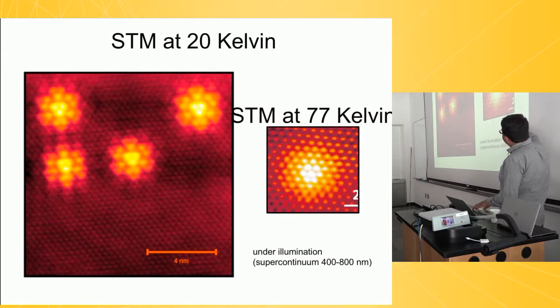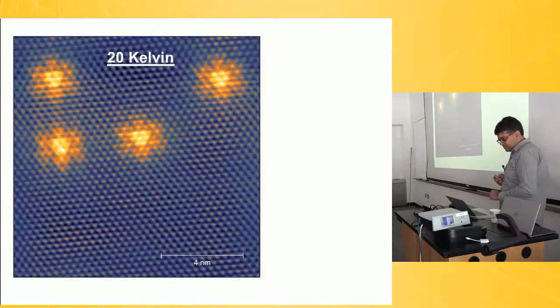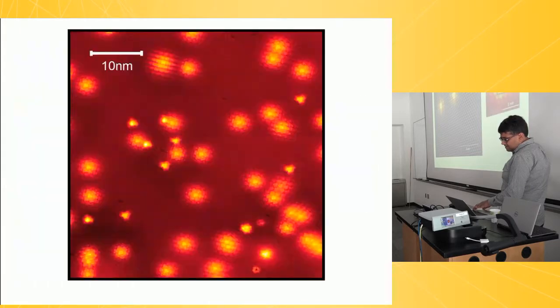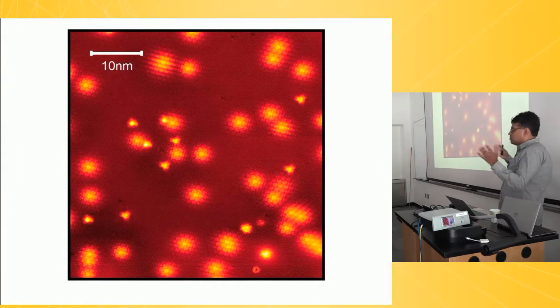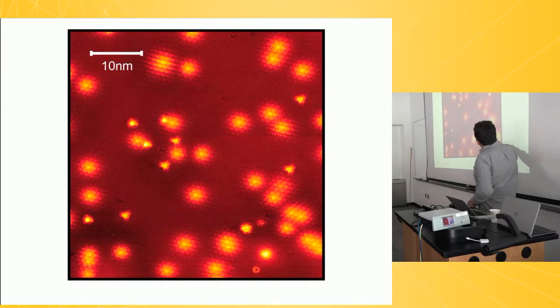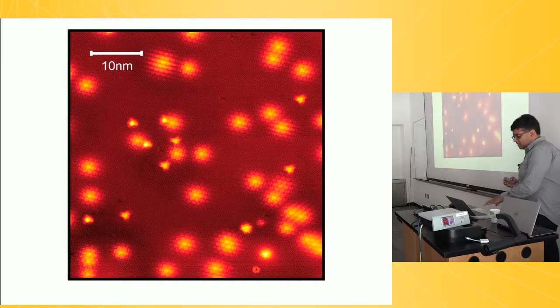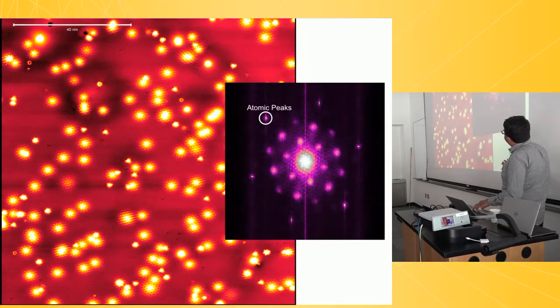And this is the same thing at 77 Kelvin. Really the difference is not so much that things have evolved with temperature spectroscopically, it's that our STM is better at lower temperature. So that's our sample, with the laser on. Here are these interesting flower patterns. And if you look on a larger scale, they're everywhere. If you ask what region of the sample do these flowery things cover? Is it 40%? Maybe, not bad. So I was very encouraged by this, and I said, well, this has got to have something to do with the magnetism. So we need to know what is this flowery thing.